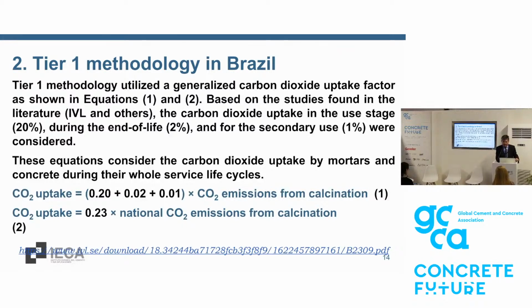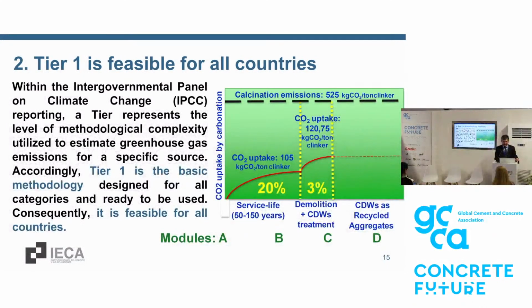All these equations are well discussed and presented in the IVL publication, and the reference is here in the slide. The schematic process is as follows. Here we can see that CO2 is absorbed following the Fick's second law, the square root of the time. And after this first period, during the service life, we have a second and third period. We have 3% more of uptaking due to the final use and secondary use. The good news is that this method is very easy and is feasible for all the countries. And all the countries can prepare and can do this estimation quite easily.